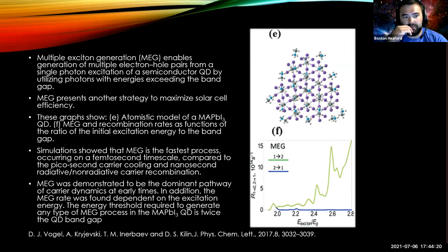And the MEG was demonstrated to be the dominant pathway of carrier dynamics at early times. In addition, the MEG rate was found to be dependent on the excitation energy. The energy threshold required to generate any type of MEG process in the methyl ammonium perovskite quantum dot is twice the quantum dot band gap. Any questions about this one?